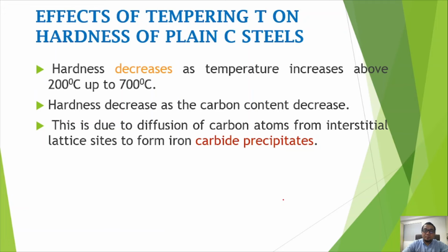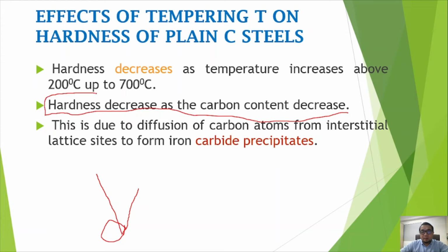So effect of tempering temperature on hardness of plain carbon steel. Hardness decrease as temperature increase above 200 degree C up to 700 degree C. Sebab apa? Hardness dia decrease sebab dia dah sejuk, kemudian dia panaskan balik. Kalau yang ni tadi, quenching tadi, hardness memang sangat tinggi, tapi dia brittle. Hardness decrease as the carbon content decrease. Sebab apa dia decrease? Dia beritahu sebab carbon content decrease, sebab dia dah berlaku semula pemanasan. This is due to diffusion of carbon atom from interstitial lattice site to form iron carbide precipitate.